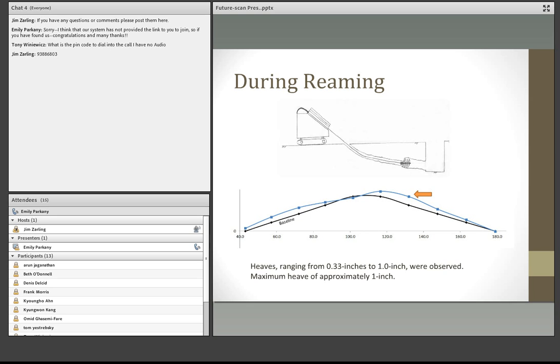As far as the results for elevations that we had taken before, during, and after pipe installation, these are the results for what had happened during reaming. So if you look, the black line on this chart is the baseline, or basically where the roadway was before any sort of pipe installation took place. And then the blue line is how those elevations have changed after, during reaming. You should also note that basically each one of these elevations were taken along the full 180 feet of pipe length and across the roadway. So we're getting the entire drill path here.